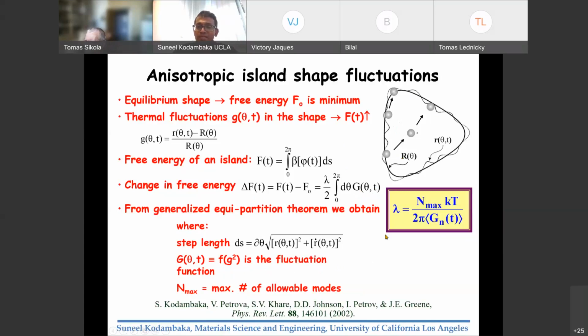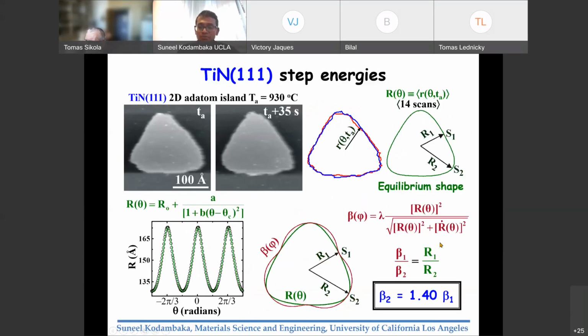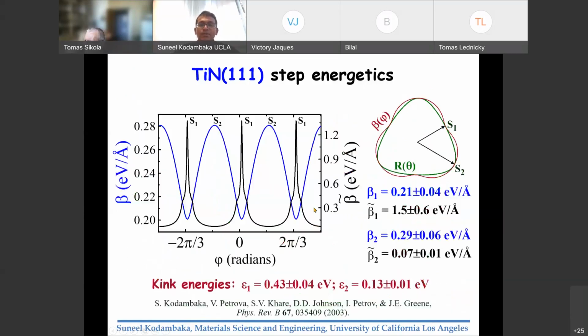And we have developed a formulation for measuring the chemical potential per unit area as a function of the fluctuation modes and the number of modes you have in a given island. And using those measurements, and again by measuring the equilibrium shapes of the islands, we can now extract step formation energies and step stiffnesses also for any given surface. Okay, and so this type of information is fairly straightforward to obtain once you have experimental measurements. And the scanning tunneling microscopy is a great tool for quantitative description of these types of phenomena.